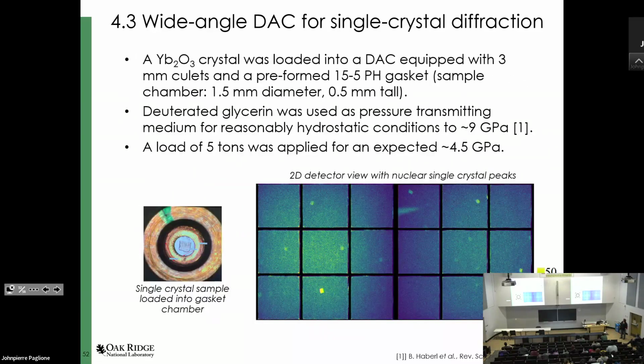So we chose a sample just based on it was something we wanted to trial this with, where we knew there is a magnetic phase transition, where we see some magnetic peaks. So we loaded this sample into our diamond anvil cell. As pressure medium, we used deuterated glycerin, which has the advantage that it doesn't evaporate that fast, so you can actually fine-tune the alignment of your sample while the liquid is already in there. And then we applied a load of 5 tons, which we expected would get us to around 4.5 GPa.